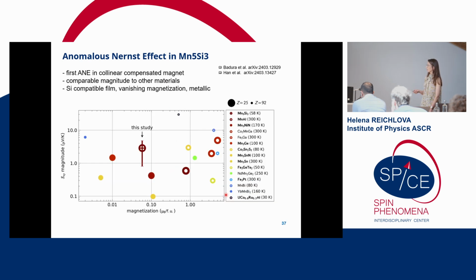And now, as the last slide, I put the values which we measured in our altermagnet into a table which compares different materials. The different materials range from antiferromagnets to ferromagnets, which are marked by open circles, and by the size of the ball I indicate how heavy the element is. When we look at the magnitude of the Nernst effect, the record large values are indeed these uranium-based compounds. This is wonderful work.